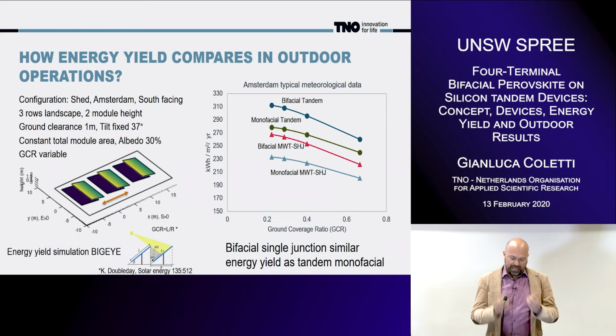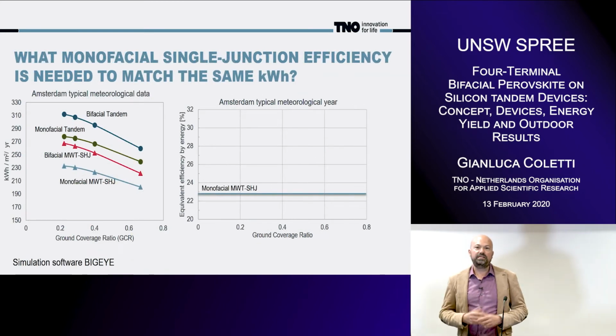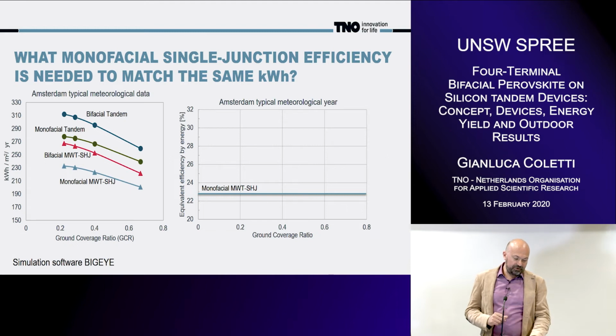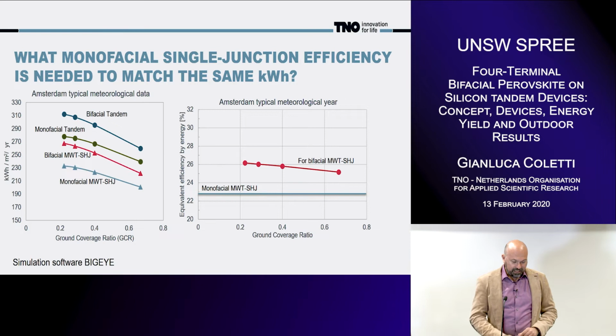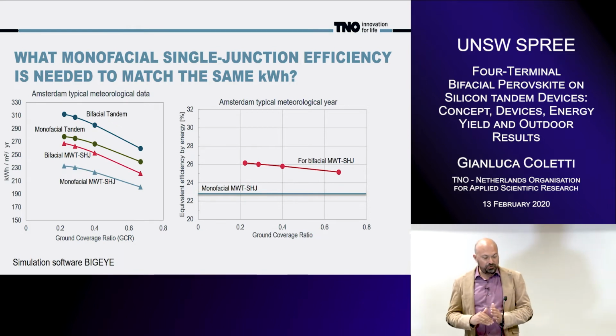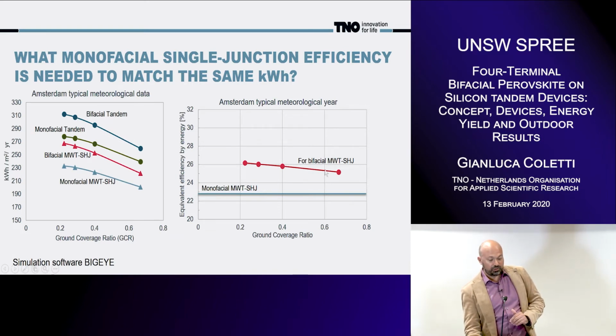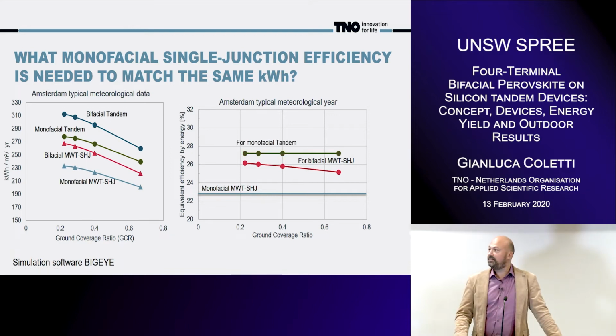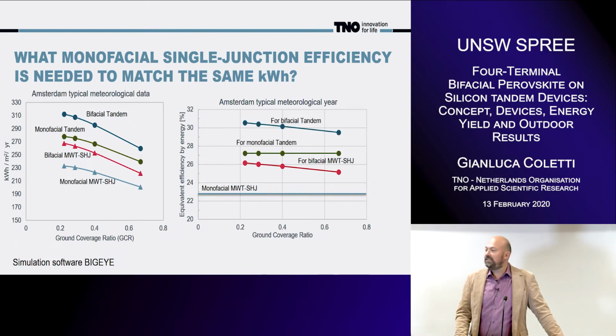So here is the real energy, how this converts into this equivalent efficiency. We use as a reference the monofacial MWT silicon heterojunction single junction module, which produces around 23%. And then you need this device efficiency to go up to 26% in order to match the energy yield of the bifacial device. And we need about 27% monofacial single junction device in order to match the same energy yield of the monofacial tandem. But look here, you need more than 30% when you combine tandem and bifacial.